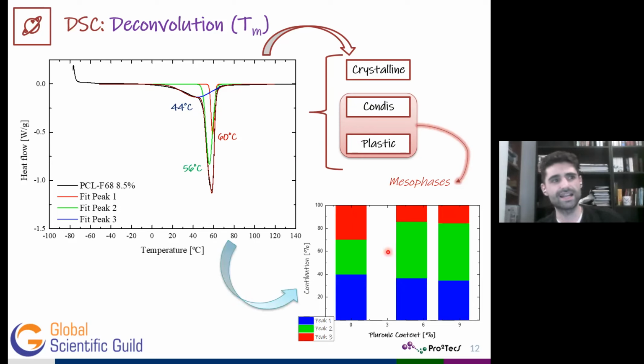Well, we analyzed the individual contribution from the areas contained in these peaks, and we observed that upon addition of Pluronic, the peak located at 56°C was promoted. But apart from that, we couldn't identify to which of them each crystal morphology corresponds.